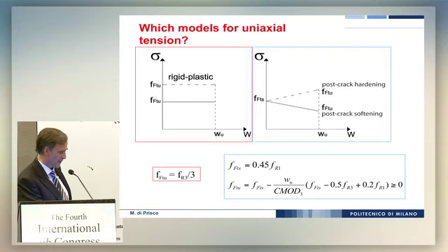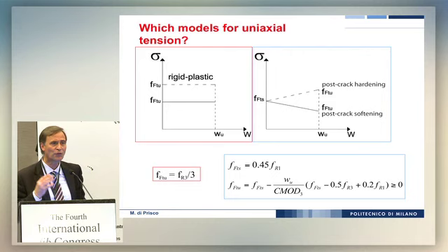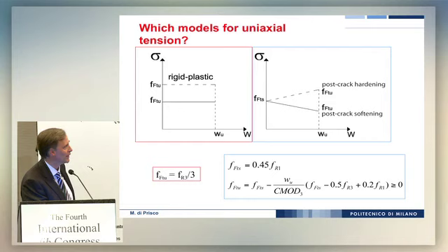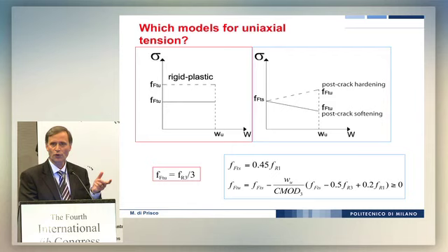on every time you need a stress crack opening law. It's also very important to highlight that due to the fact that we use this material after the cracking of the matrix, we always define the constitutive laws as stress crack opening, not stress strain. So we have a problem to passage from stress crack opening to stress strain.